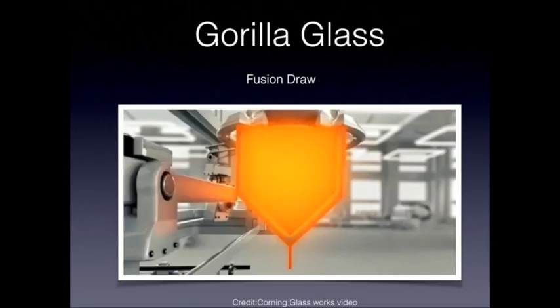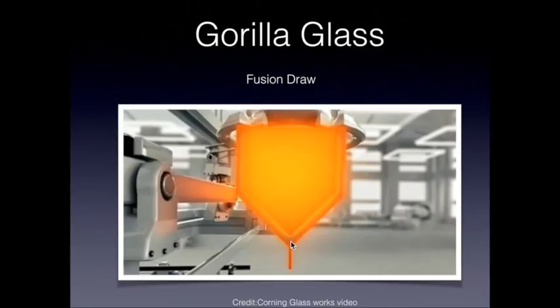What you're looking at is essentially the end of a long trough — not unlike a gutter — that is filled with molten glass. You can see the dark orange on the outside where molten glass is flowing around it. The process involves filling this trough with molten glass and continuing to fill it so that it overflows the sides, runs down on both sides, and then meets at the bottom — forming a long molten sheet of liquid glass.